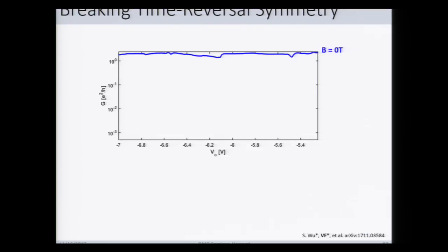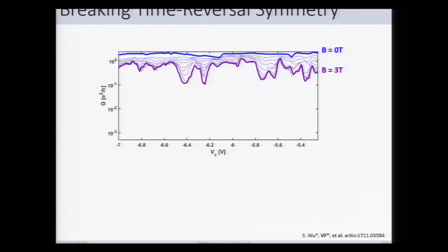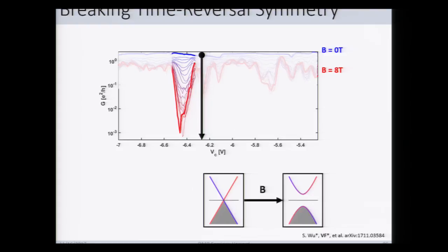So, okay. This plateau resistance that I've shown you, we've inverted to conductance here. And so we have this curve at zero magnetic field as a function of the local gate voltage. You can think of this as a chemical potential. And as we turn on a magnetic field, initially, the conductance generally drops. All right? So that's the first stage of what we observe as we turn on a magnetic field. And then as we turn it on a bit more, you can see that, I'm going to go back and forth a few times, here on the left and on the far right, not much happens in this second stage, except right here where we see another full order of magnitude reduction of the conductivity as a function of field. And we can keep going, and you see here again that it is dropping precipitously. Note the log scale, by the way, on the y-axis.